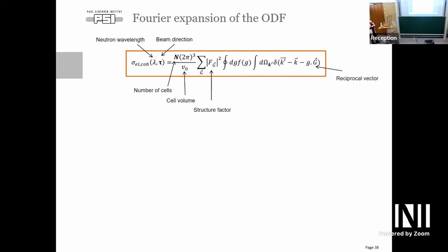So this thing has been puzzling me. What I have in mind is that some crystallographic planes don't have so many atoms, nuclei, in the plane, right? So it doesn't give such a strong reflection. And that's in the structure factor, right? Yeah, the structure factor basically means, if you have a crystal cell, how the atoms are arranged there, which will be different for different structures, BCC or whatever. You have to take into consideration which atoms are in which position. That means we change the way that the entire cell will contribute, right? Okay. And is it known? Can you calculate it? Yes, I can calculate it from neutron data.